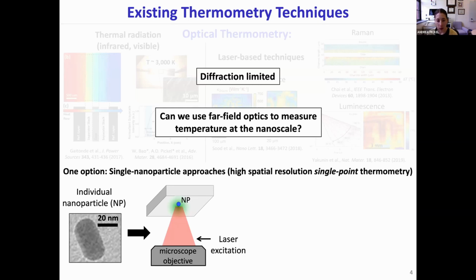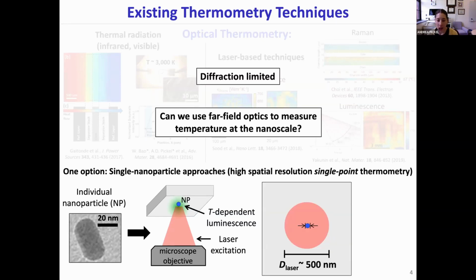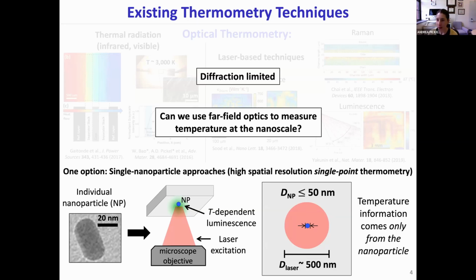We then excite the nanoparticle with a laser and measure the temperature-dependent luminescence it emits. And because the nanoparticle is very small, this minimizes issues of parasitic heat sinking and thermal contact resistance so that the nanoparticle can accurately report the true sample temperature. Even though we're still exciting the nanoparticle with a diffraction-limited laser beam, the key is that the temperature-dependent luminescence and therefore the thermal information come only from the nanoparticle, whose size is much smaller. And so as long as we're only exciting one nanoparticle at a time, then the spatial resolution of the temperature measurement is governed by the nanoparticle size.